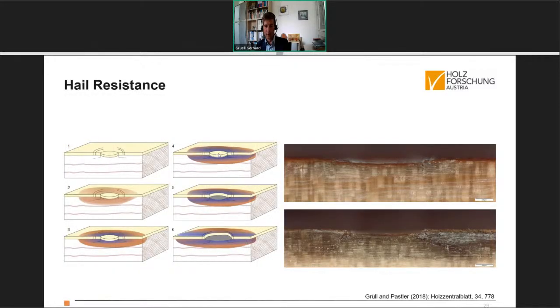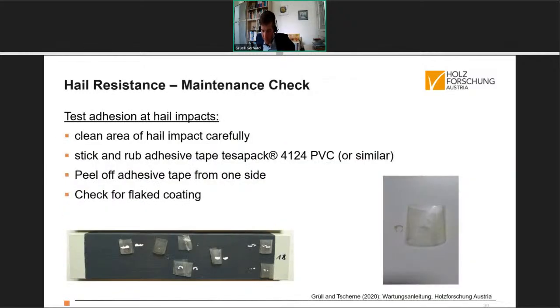In our research, we have described the degradation and the ongoing development of defects under hail impacts in schematic images and also with microscopic images. But for maintenance, we found a very important conclusion that, as I said before, maintenance can be done as long as the adhesion of the coating is good. And that's why we suggest in the case of hail damage to use a test like this with a simple adhesive tape, clean the area of the hail impact, stick and rub the adhesive tape on the surface and peel it off. And then you see whether the coating flakes or not, which is an indication if the adhesion is lost, and you can still put a maintenance coat on top of this surface.